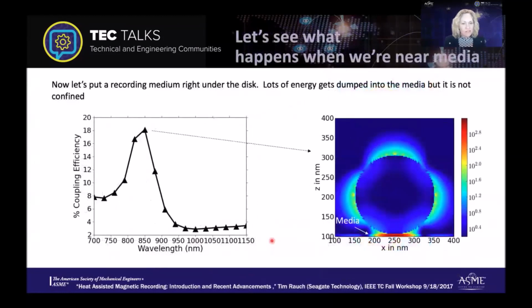So we've got this efficient coupling of the light into the sphere. Can we use those surface plasmons on the surface to transmit energy into the disk? What if we put disk media really close to that sphere? We can see that we can actually get a lot of the energy from the laser coupled into the disk and now into the media. But it's still not very confined. This is still about 100 nanometers in width. It's smaller than focusing it, but it's not as small as we want.